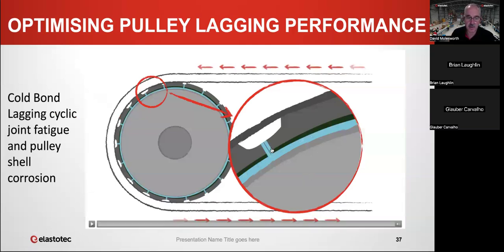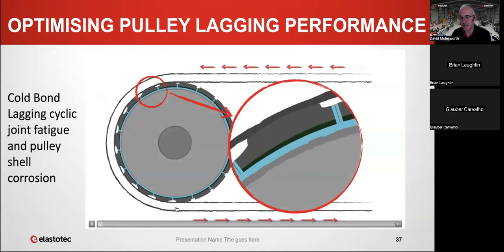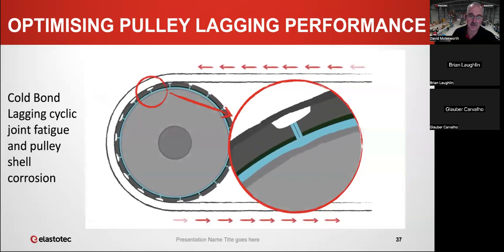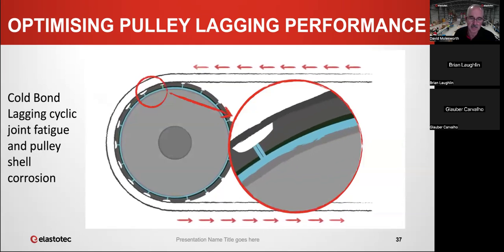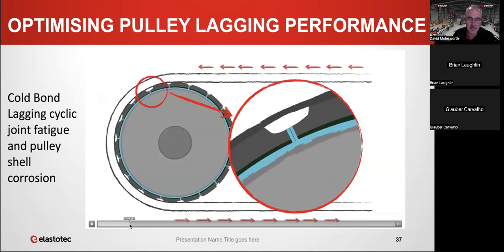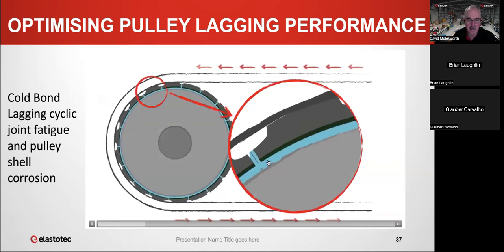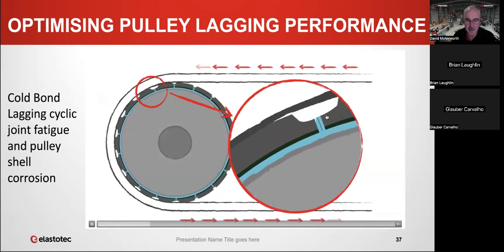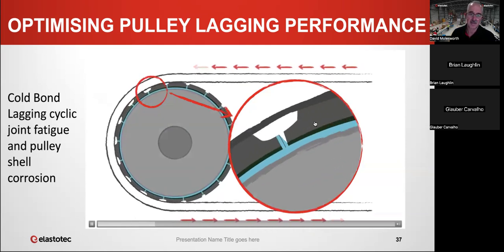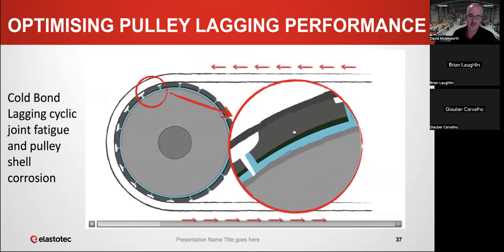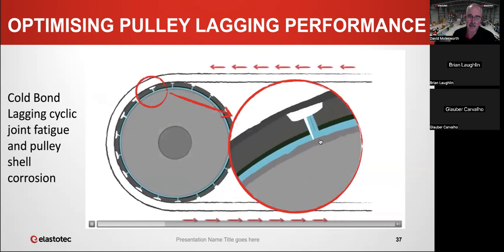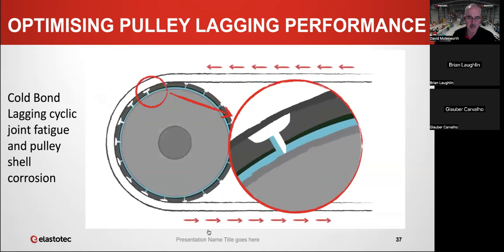Before I mentioned about this weak point, this is this point here between the lagging where this bonding layer doesn't exist up the sides. You've just got the adhesive. I'll just show you on this graphic. So again, cold bond lagging, just like hot vulcanized lagging, gets exposed to stresses as the lagging contacts the belt, goes around the arc of contact and then unloads. And basically what happens, you get an initiation of tearing up at the top here because it's the weakest point. The neoprene adhesive doesn't bond as well. Eventually, that will open up and give you a pathway all the way to the shell, the pulley shell.